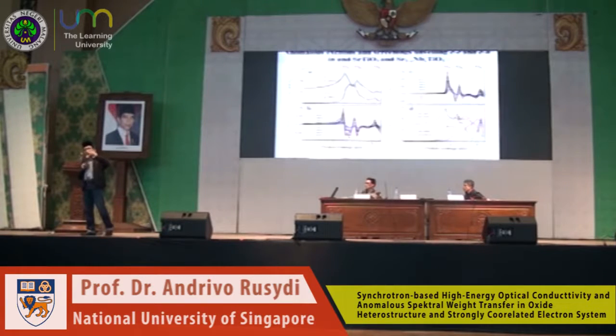What does it mean? It means that if you place something on STO, whatever thin films, graphene for instance, or a 2D material, it might change the optical conductivity dramatically because of the correlation. Right? So we test our knowledge. We challenge whether our knowledge is correct that STO has the electron-electron-hole interaction: place graphene on it, and the optical conductivity of graphene should change dramatically as well.